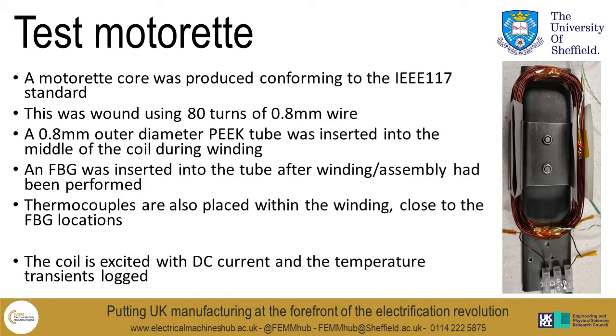So to perform some testing on these temperature sensors, we produced a motorette, as you can see in this slide. The specifications of it basically conform to the IEEE 117 standard for the core. The winding is an 80 turn 0.8mm wire winding, and a 0.8mm outer diameter PEEK tube was used to protect the temperature sensor from the external strain. This was inserted into the middle of the coil by stopping winding halfway through and placing the tube and then completing the winding. We also, for reference, attached a couple of thermocouples which were located at relatively close positions to where the FBG sensors were in the assembly, which gives us something to compare the temperature measurements to.